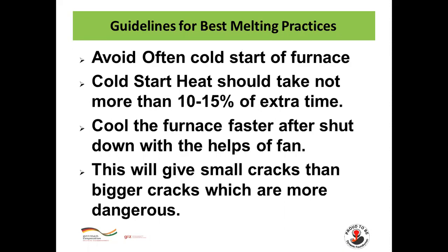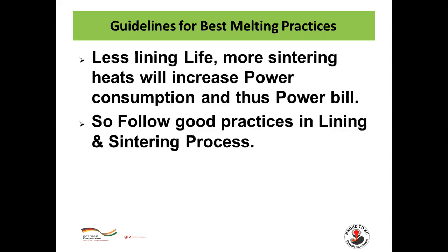Avoid frequent cold starts of the furnace. A cold start heat should take not more than 10 to 15% of extra time. Cool the furnace faster after shutdown with the help of a fan. This will give small cracks rather than bigger cracks, which are more dangerous. Less lining life and more sintering heats will increase your power consumption and thus your power bill. So follow good practices in lining and sintering process.